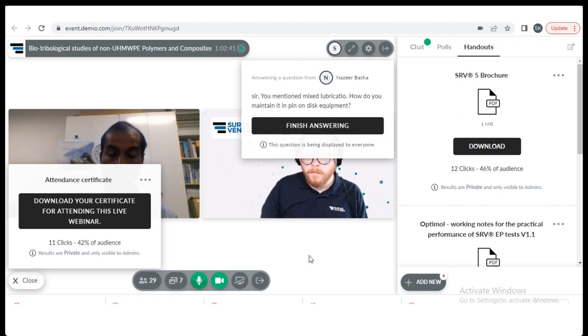Yeah, so basically people have proposed that it is a mixed lubrication, and we have also seen through our various tests, using some of the models. You will have to go to some of our other papers where we have shown that mixed lubrication can be proven if you measure friction and the speed. There is a relation between the friction or the shear stress and the speed, and under some situations you can get a linear curve. This proves that mixed lubrication was working, and in fact there is a famous paper by Hugh Spikes from Imperial College. If you are interested, please go to that paper, and also a very classical paper by Professor Brian Briscoe, also from Imperial College. And if you go to our papers as well, you will find that it's possible to actually prove that there is a mixed lubrication.